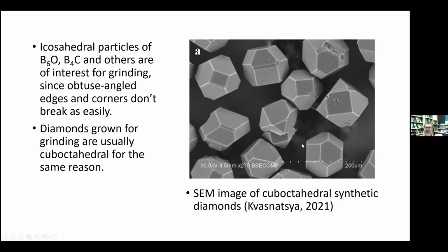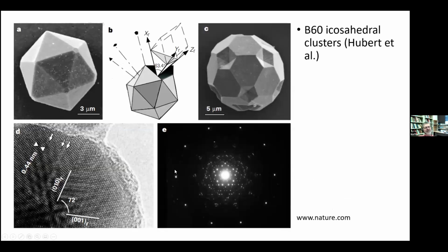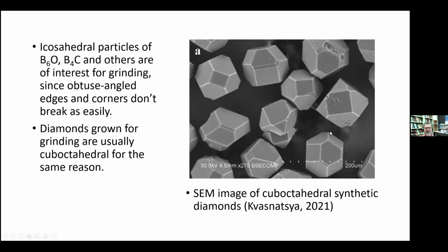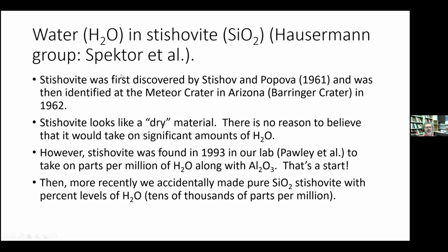But so they grow it in intermediate temperatures to get these cube octahedra. So these, you could imagine, especially B4C, which is a very important grinding material, but also B6O potentially could be used as a grinding material. They're all super hard. B4C is the third hardest material, at least the third hardest commonly used material after cubic boron nitride and diamond.